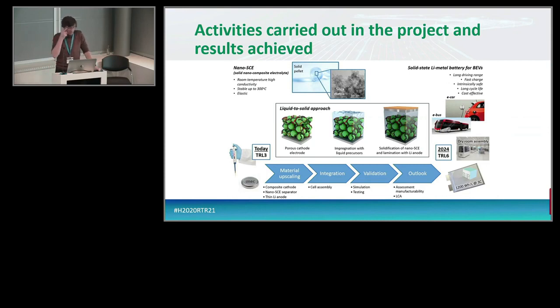Just on top, a schematic picture of the solid electrolytes, what we call our nano SCE. So basically you can see a pellet after solidification. It's indeed solid, it's a pellet. And if you zoom in, it's basically a silica matrix with some electrolyte material surrounding it. To be able to do that, we needed to work on the material part, both on the composite cathode, the nano SCE, and the lithium anode, together with the different partners we are working with. I'll give a few schematics for that in the next slides. Of course, we also have to do the cell integration, validation, and then assessment of manufacturability and cost to indeed show, look, is this indeed possible to do beyond TRL 6.